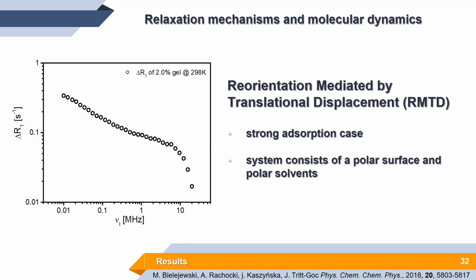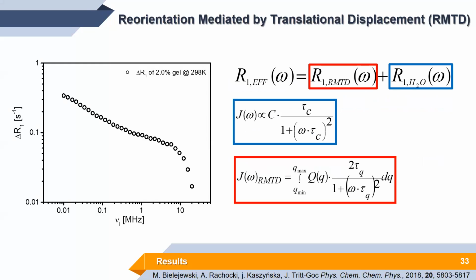And this makes the fluctuation of the orientation, or reorients the spin system by translational displacement on the surface of the gel matrix. And because of this, the RMTD process is an effective relaxation mechanism of liquids confined in porous media, especially well seen at low frequencies. So to describe this effective relaxation rate, in the case of our reference system, we can assume two contributions.